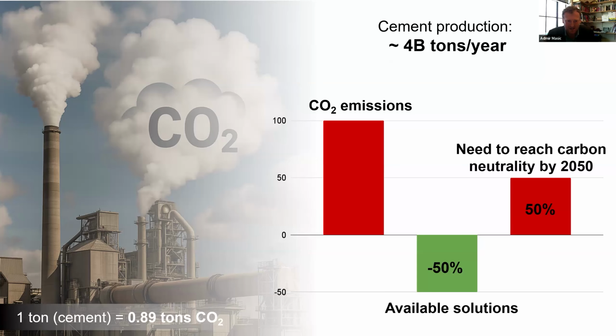And when it comes to concrete and cement as a binding material, for each ton of cement produced, we emit a significant amount of CO2 into the atmosphere. It's about 0.89 tons of CO2 emitted for each ton of cement produced. And current production, which is projected to increase, is 4 billion metric tons per year, which translates into significant CO2 emissions. Unfortunately for us, we currently have available solutions to mitigate about 50% of these emissions. And in order to reach carbon neutrality, which should be our goal by 2050, we still need solutions for the other 50% of these emissions.